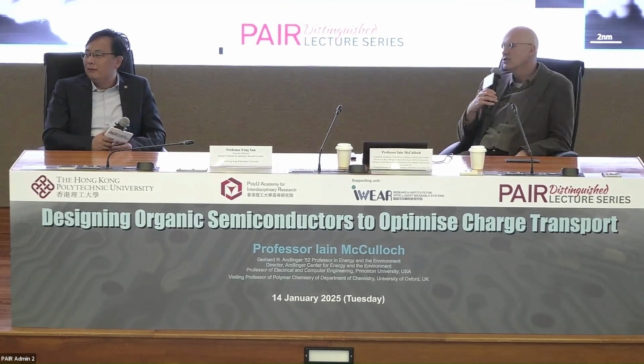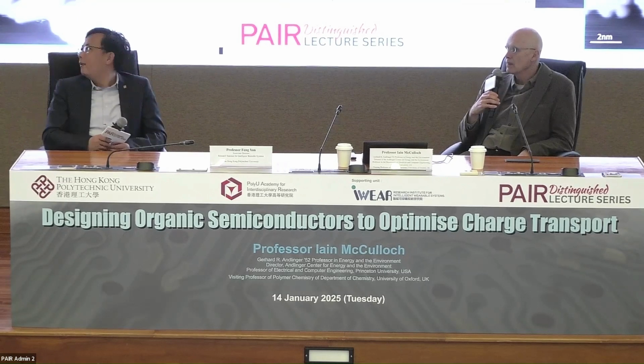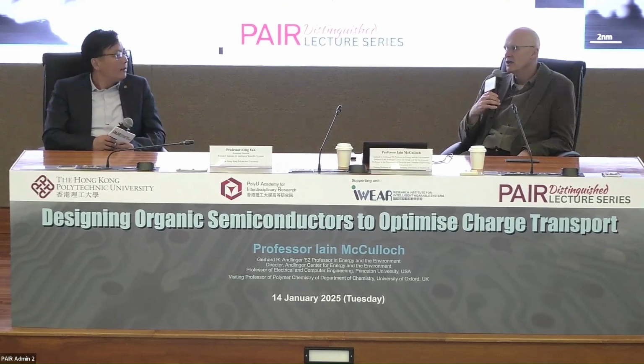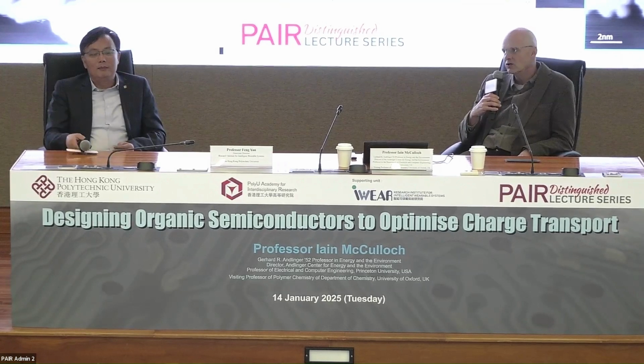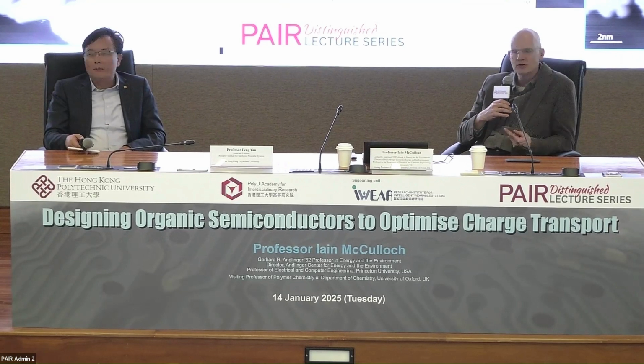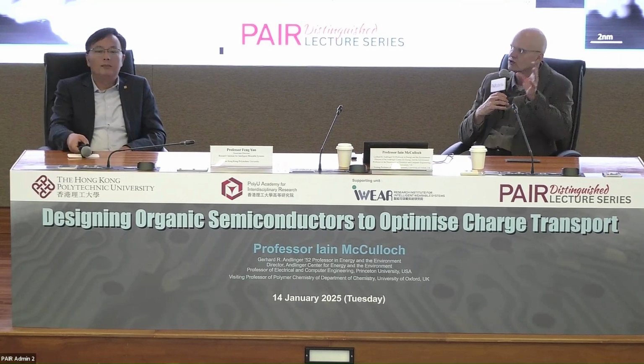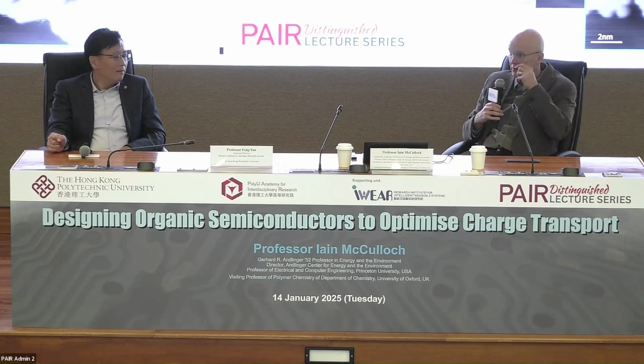That's amazing. We see that more actually from TEM. So we have to do a lot of cryo TEM to avoid that. And we use as low a beam intensity as we can. But we still struggle with the TEM, actually for nanoparticles, we're looking at heterojunctions. But when we move to the cryo, it tends to reduce the beam damage a little bit at least. But I'm not an expert in microscopy, so I can't really comment much more than that.